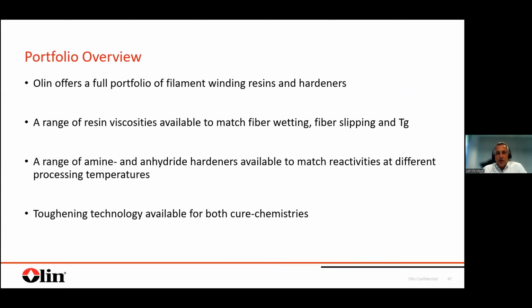We have two different hardener chemistries available in our portfolio. On one hand, the amine hardeners, which have benefits with regards to curing at lower temperatures, and the anhydride hardeners, which have their benefits in being very low reactive at room temperature, even kind of latent. And last but not least, we have the toughening technology available for both of these cure chemistries.